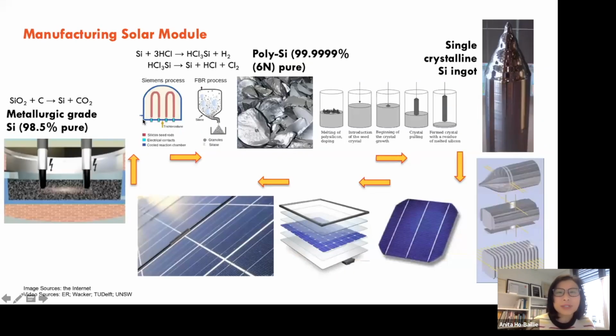Okay, so the incumbent technology is based on silicon. And here you can see that the way it's manufactured is quite a time-consuming and energy-consuming process. So you start from quartzite, and then you've got to purify it to metallurgical grade silicon, and then you've got to purify it to a silicon with 6 nines impurity, meaning 99.9999% pure. And then you've got to regrow it again to make it into a single crystalline form. And once it's in the ingot, you slice them into slices. So we call them wafers.